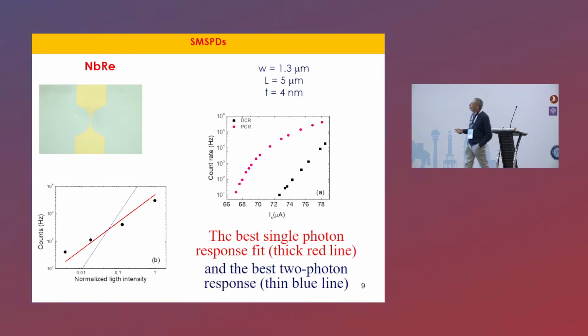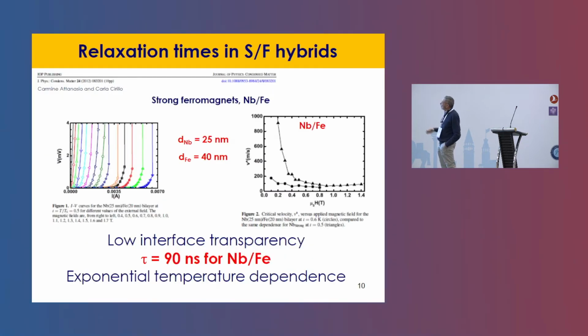Maybe this is even more important, because this experiment has been done on niobium rhenium thin films, 4 nanometers thick, on a wire, so this is a microstrip superconducting single photon detector, and you can see here that we have been able to detect single photons. So I say this for us is much more important because this is a very easy geometry. So I mean, you don't need to go to Delft to convince people that they have to do very, let's say, advanced things. So this is for a study of feasibility. It's very important for us. And as I said, these are still unpublished results.